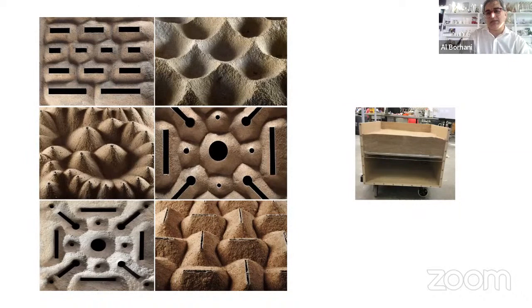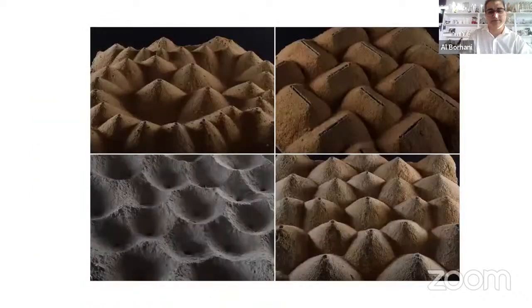A student made a shoebox. It was really the end of the semester, and they were almost broke in regard to spending more for the studio, but they made 2 feet by 2 feet boxes, and they tried to make this concrete shell by using sand. They used sand as a formwork and simply used sand several times. Some examples of the front side and back side of the shells.